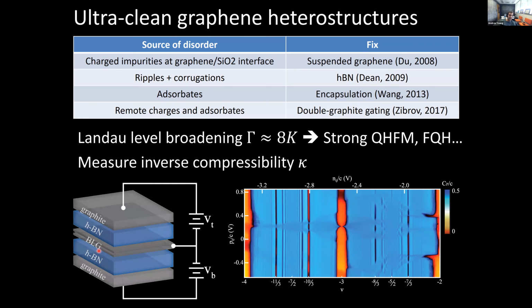is an incompressible state, so think about a system with a gap, then a small AC electric field on this graphite will simply penetrate because this bilayer cannot screen, whereas if it's a highly compressible state, then that electric field will be screened and you'll see no current on the top gate. And so mostly I'll be showing you measurements of this inverse compressibility, which is what this probes.